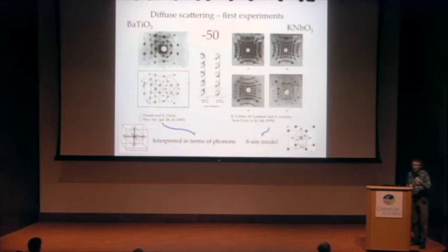So this piece of evidence gives a very intuitive and simple understanding of the temperature phase diagram. In terms of configuration and entropy, it's very easy to understand that if we occupy only one of the eight sites, there is no more diffuse scattering, no more disorder.